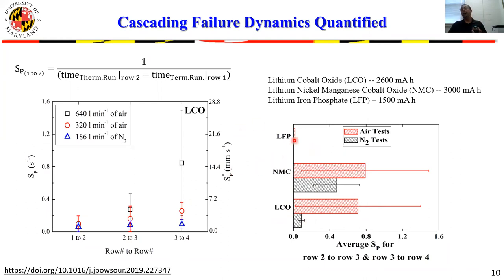LFP did very well on this test. In essence, in about five tests in nitrogen, if I remember correctly, none of them propagated thermal runaway. And we achieved propagation of the thermal runaway only in one air test. So these results for the LFP looked rather promising. That improved safety, of course, doesn't come without costs. LFPs have about half the capacity of these other cells. So if you'd like this increased safety, the capacity of the cells has to be sacrificed, at least within this realm of chemistry.